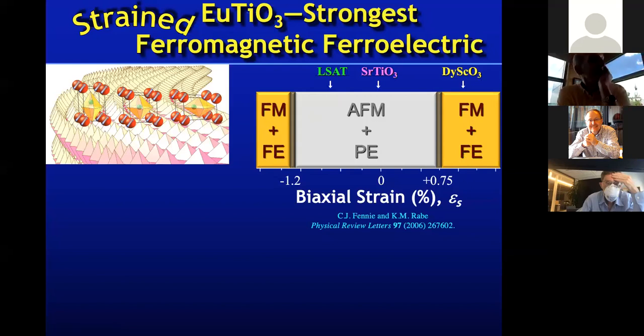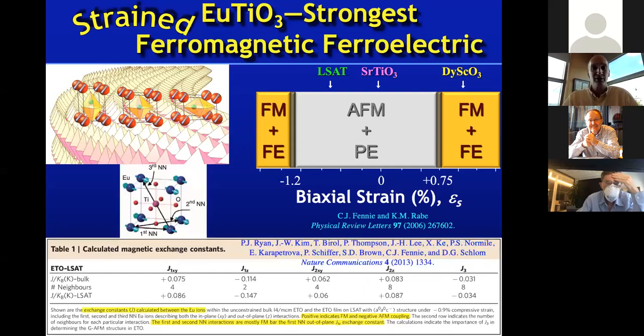In fact, their prediction was quite astonishing, because they predicted that this material should have robust ferromagnetism, 7 Bohr magnetons, at the same time that it has robust ferroelectricity, about 10 microcoulombs per square centimeter. Which, if true, would make it the world's strongest multiferroic material. So, of course, there was a lot of experimental work, and we were actually the 4th group to publish on this, but I'll tell you about our results. But I also want to talk first about the inner workings of Craig's calculations of what's going on.